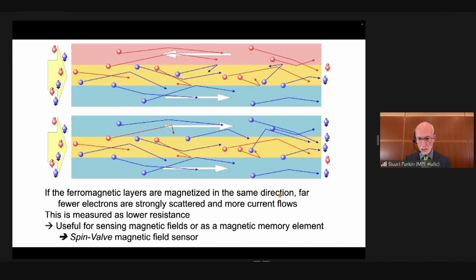In reality, in the sensing configuration, the magnetic moments of the two layers are designed to be orthogonal to one another. This gives rise to a maximal change in resistance in the presence of small magnetic fields. And another very important characteristic of these structures is that a magnetic moment will give rise to dipole stray fields. And in this configuration shown on the top, the stray fields from the lower layer will be attractive to the upper layer, and it lowers the energy of the system.